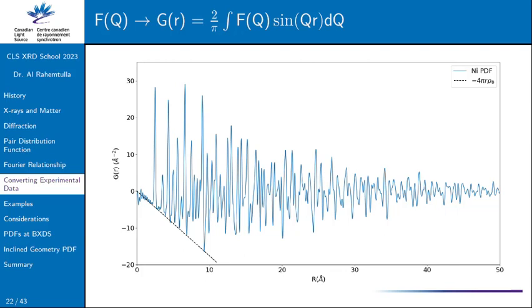Yeah, so even for amorphous, there could be short range ordering, right? If you imagine any compound, there's still some chemistry there, so you'll actually see atom-atom histograms. Let's see, this is going to look a little messy, but imagine this is our origin atom. Let's pretend this is a nice little circle. We'll call that 2 angstroms. That means in this RDF, there's going to be a sharp peak at 2, and the area of this peak is going to correspond to 4 atoms being there.